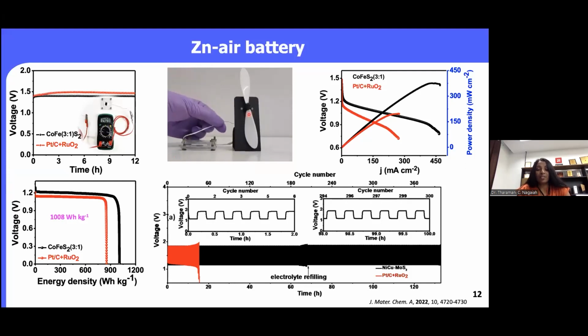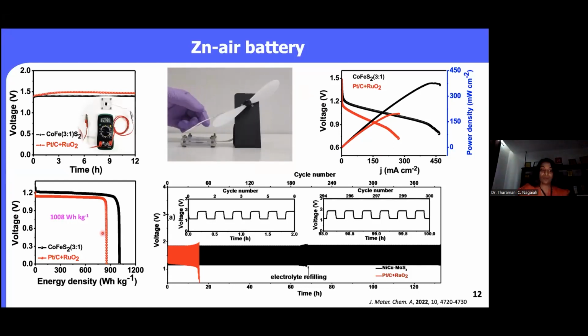Okay, so this is a demonstration of the zinc air batteries which we connected to the fan, and you can see that without any external power source, we are demonstrating that we can run a fan. And we have calculated the power density, and the power density is found to be 350 milliwatt per centimeter square. And also the energy density is quite high in the case of our proposed catalyst, which is about 1008 watt hour per kg. And also when compared to the platinum carbon, this is quite stable.